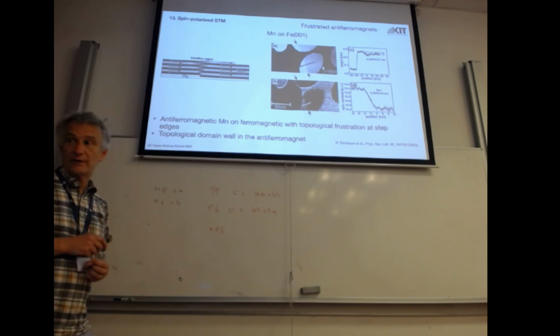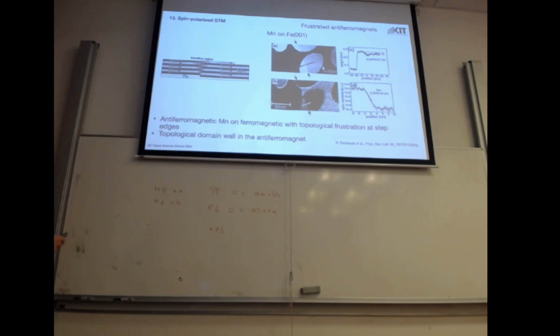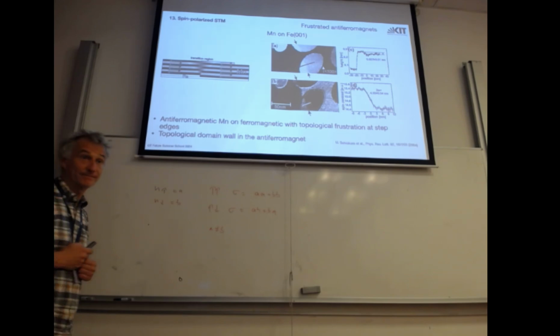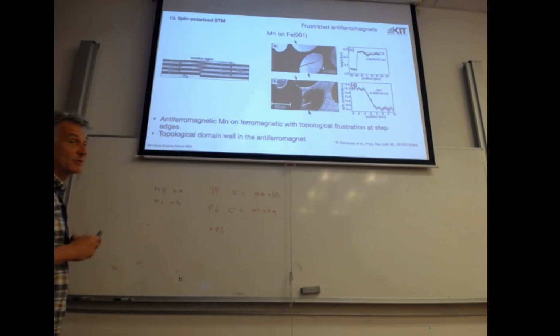But iron is not flat. All of the crystals always have steps. So let's assume there's a step here. So this one is ferromagnetically coupled, and this one is ferromagnetically coupled iron. But here the first layer touches the second layer. You have to frustrate the system. There's a transition region here due to frustration of the competing exchange interaction, and an antiferromagnetic domain will form. Luckily, iron and manganese atoms are not the same size, so these kind of buried steps show up in topography.